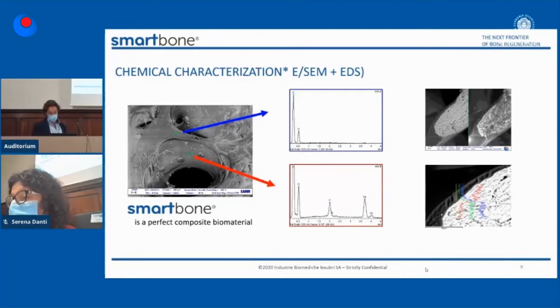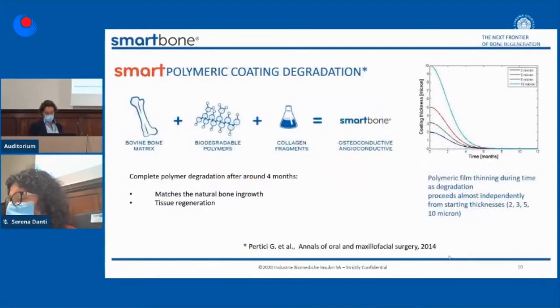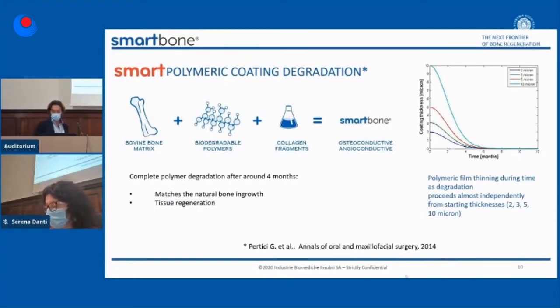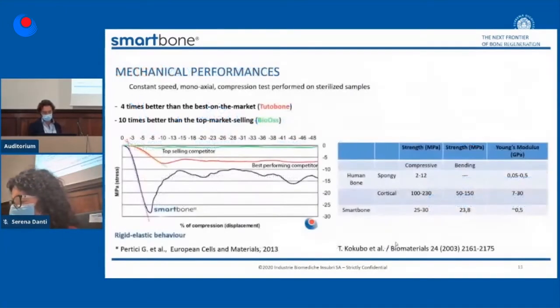Here you can see, in the red arrow, calcium phosphate, so the xenograft material, while the blue arrow shows the coating that we put onto the material. It's a very, very thin coating, around 10 microns. We know from some analyses, but also from the literature, that after 4 months this polymer is completely degraded by hydrolysis. So there is no strange reaction or degradation of this material.